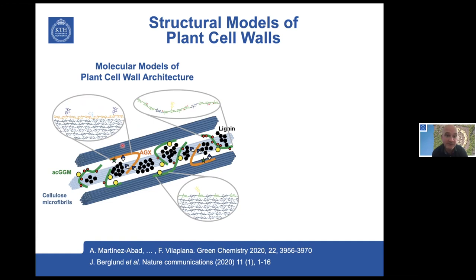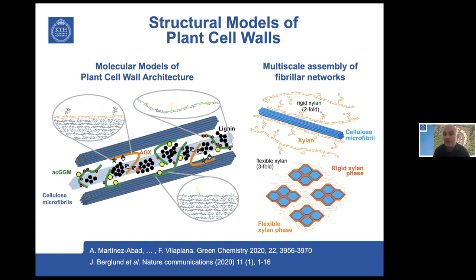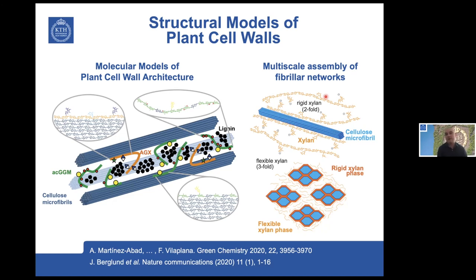On the other hand, you can also find motifs with high clustering of glucuronic acid that interact with the phenolic components — a big implication for plant cell wall assembly. We also found that molecular structure influences how hemicelluloses assemble: we can find rigid layers of hemicelluloses closely adsorbed onto cellulose surfaces, and also flexible xylan components. Having xylan drastically increases the ductility of fibrillar networks, and having mannan drastically increases their compressibility.